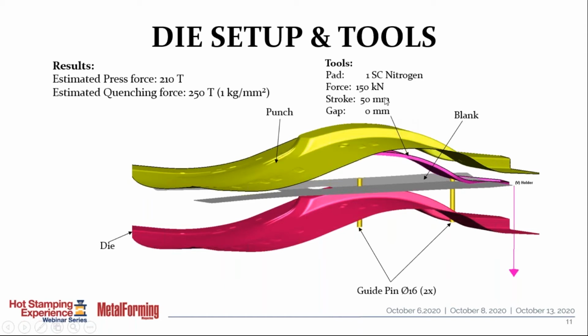In this case, we looked at a 50 millimeter stroke pad with no gap to kind of lock the material on the post, and then the cavity would come down and form around that punch, or the die technically, in order to wrap the material around that form. The big forming area here is this particular area.